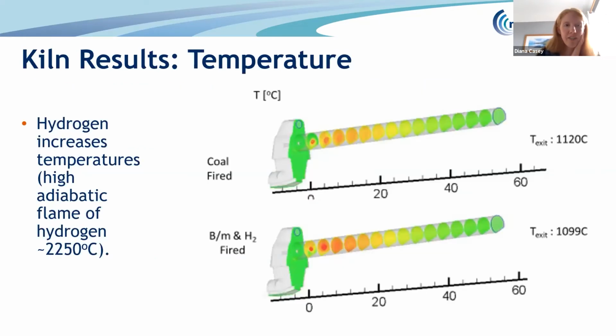These images now show the difference in temperature for the two situations. The red sections are the higher temperatures. In this bottom diagram with the hydrogen, you've got a lot more red at this end of the flame, showing a short, sharp hydrogen flame compared to coal, where the heat spreads and disperses a bit more. You can also tell the flame is a bit shorter because the exit temperature for the hydrogen case is lower than for coal: 1099 degrees C for the hydrogen and 1120 for the coal.